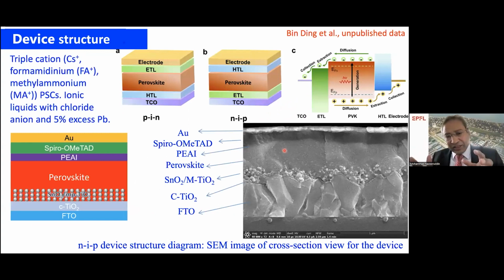Once you have these materials, there are several device configurations, but for the sake of the audience and the students, I have taken two main configurations. One is called PIN, and the second one is called NIP configuration. It's the way you deposit the various layers. In the NIP configuration, the light passes through the electron transport layer, followed by the perovskite, and then the hole transporting material. Therefore, the ETL layer has to be transparent here.